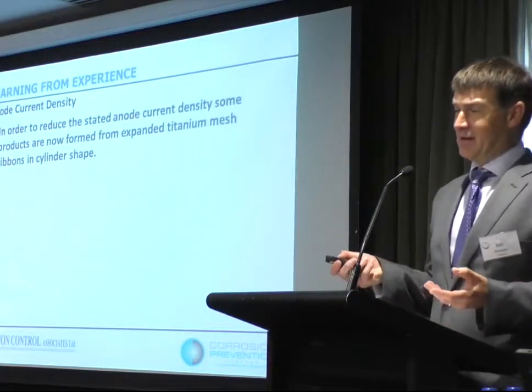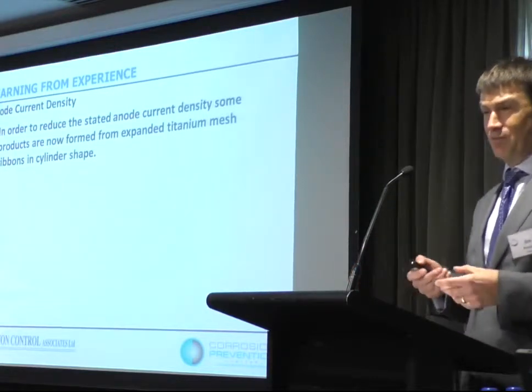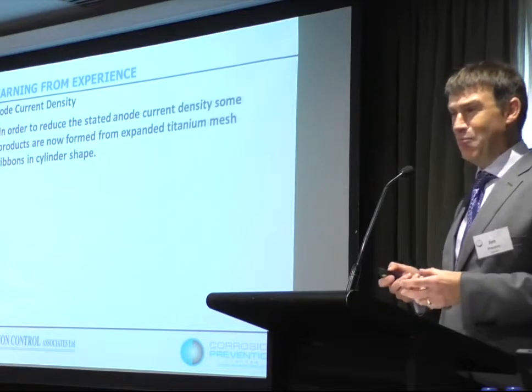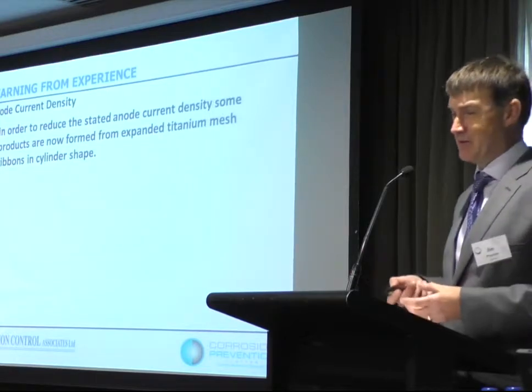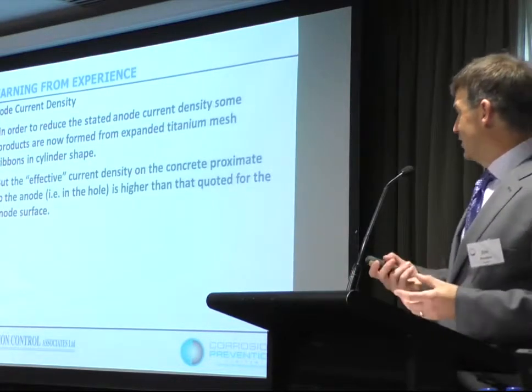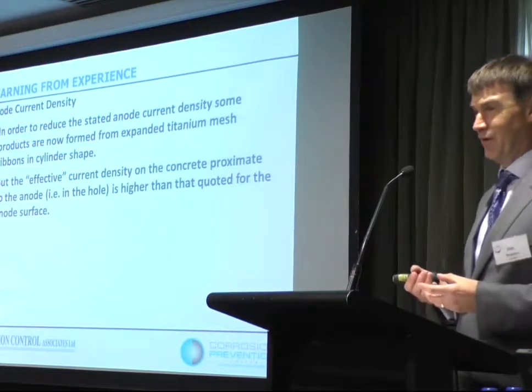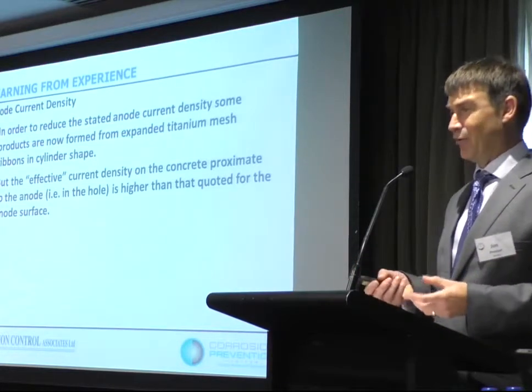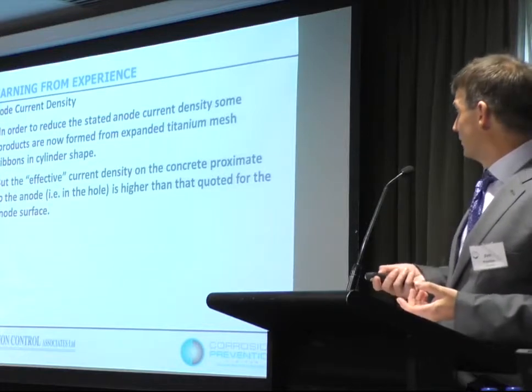We're seeing now on the market discrete anodes which are formed of mesh or different shapes to try and get more current out of effectively the same surface area or of a cylinder. So the effective current density on the backfill is higher, even though we're limiting it on the anode.